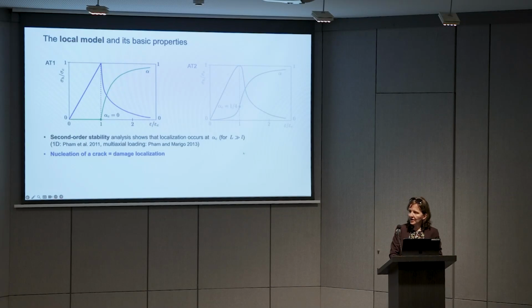And this means that you nucleate a real crack, because for us nucleation of a crack corresponds to having localization of damage. Otherwise you just have some smeared homogeneous damage, but you don't have a real crack. So this is why second order stability is very important. And this allows you also to interpret this stress as a critical stress, and so as a material strength, because this is really the value of stress at which you nucleate a new crack.